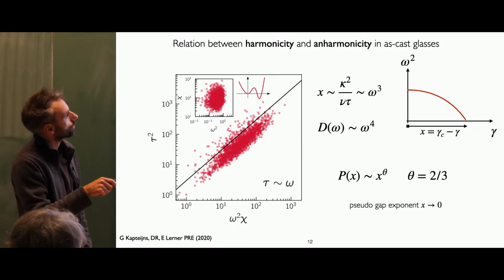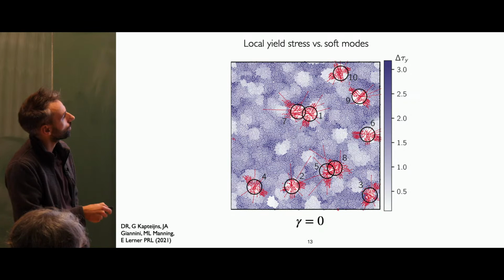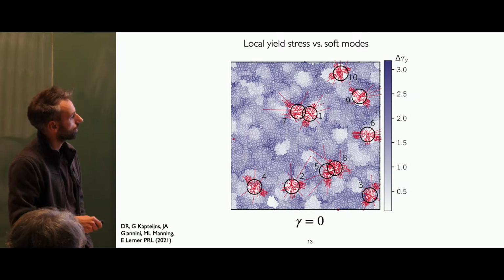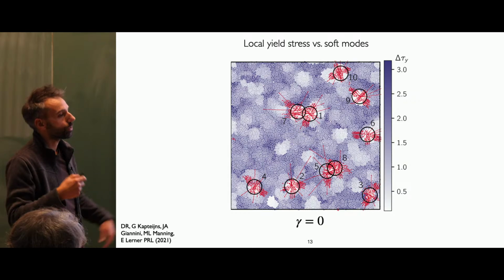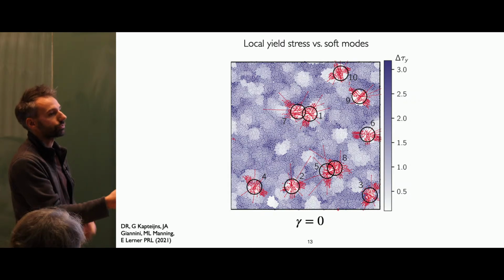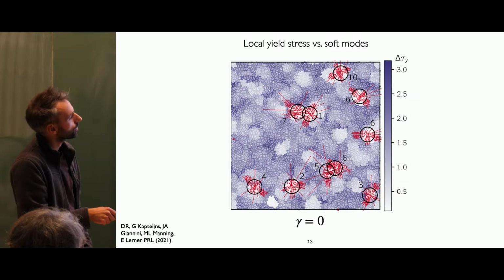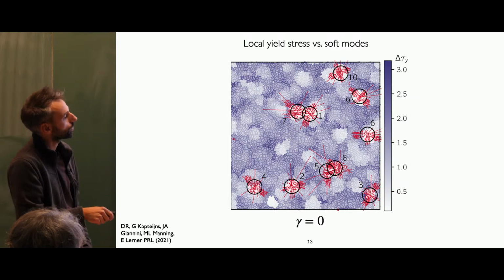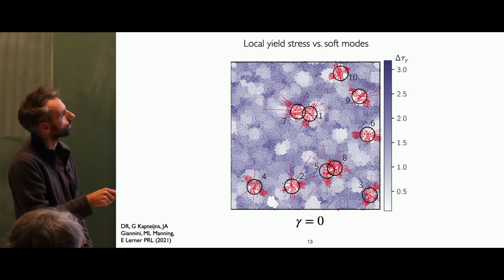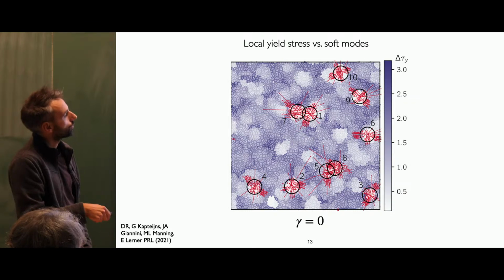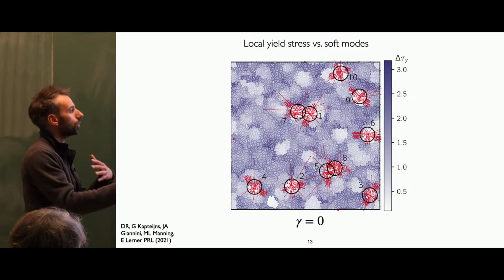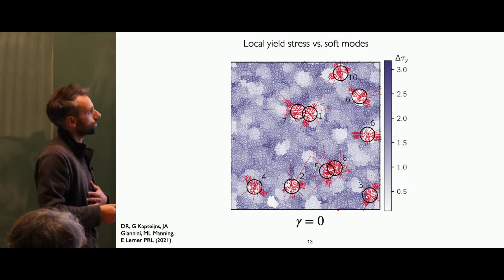And so this relation between distance and frequency, visually, what does it mean? If you take a piece of glass and you apply the local yield stress, everywhere in my system I'm measuring how much stress I need to put to yield in a specific geometry. The white regions will be the ones that are very soft, the ones where you will see plastic instability, which are marked in black circles. If you do this mode analysis already in the as-quenched glass, so at zero strain, you see that indeed in those regions with small local stress, you will have a soft mode. So that's making a connection between small local stress and soft modes in the system.